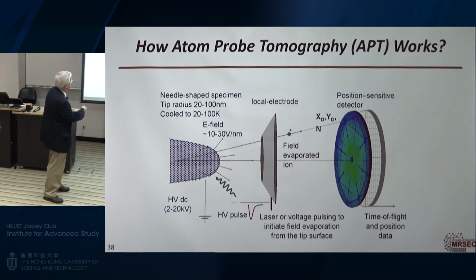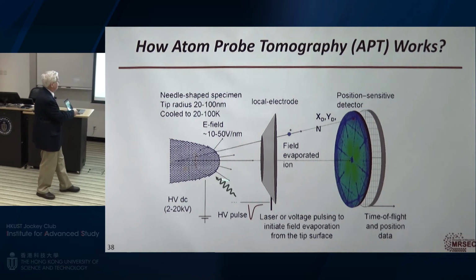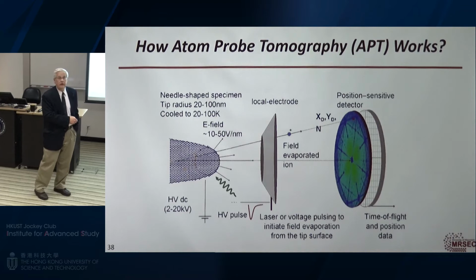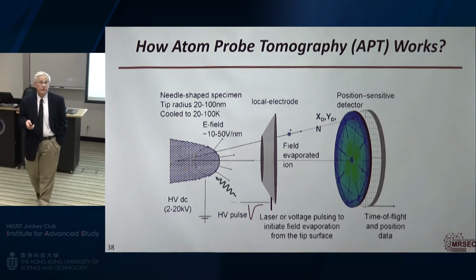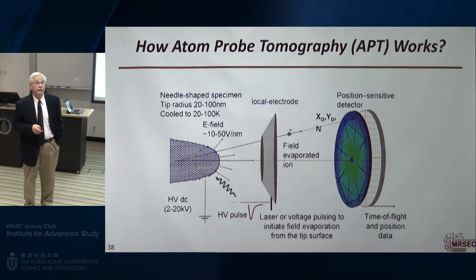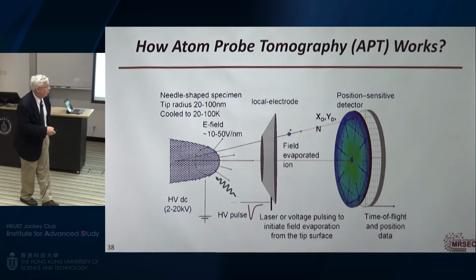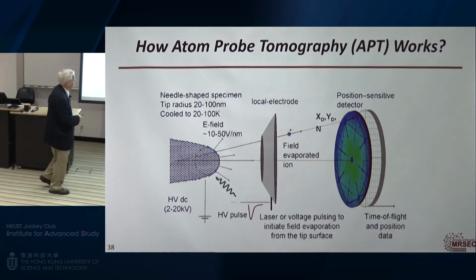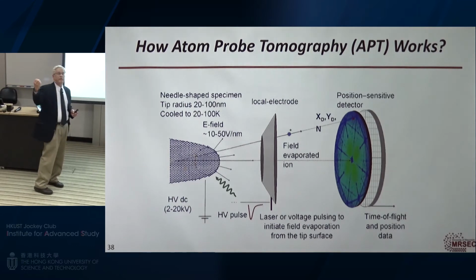And then we put it under a very, very high field, 10 to 50 volts per nanometer. So this is grounded, and you have a big field here. When I pulse this with a high voltage pulse, one atom will come off on average. Actually, one atom will come off every 100 pulses. I'm pulsing this at hundreds of kilohertz, and every once in a while, an atom gets ripped off the surface under that high field. When that atom gets ripped off, it follows the field line all the way through and hits a detector.